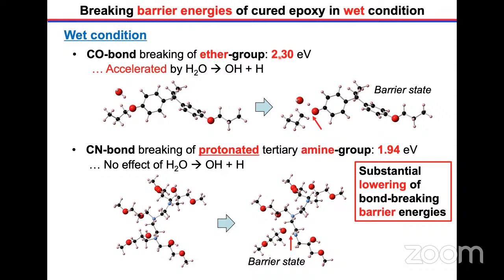This is much smaller compared to the dry condition. For the CN bond breaking, in this case a protonated amine group exists. That means that it is only 1.94 electron volt. This is the lowest barrier energy of breaking a bond of the cured epoxy molecules in water. So that means that the substantial lowering of bond breaking barrier energies occurred by the protonation effect.